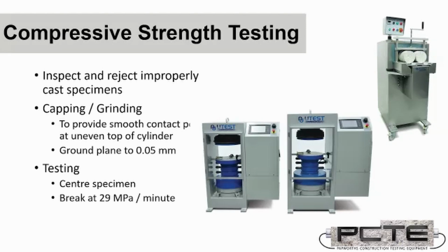To prepare them to break, they have to be cleaned up so that they've got a flat, flush surface, which could be the use of something like rubber capping, grinding to a flat surface, or the use of cement sulfur cap. So the cylinder is entirely parallel top and bottom. And then it's placed into the compression testing machine and broken with a load rate of 29 MPa per minute.